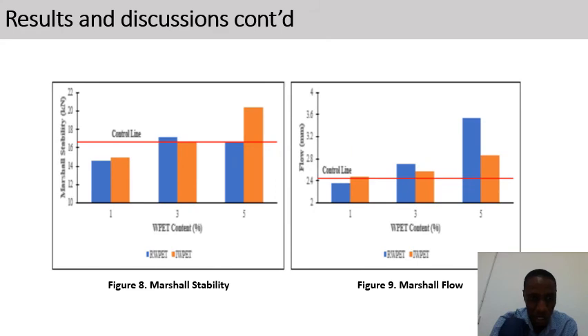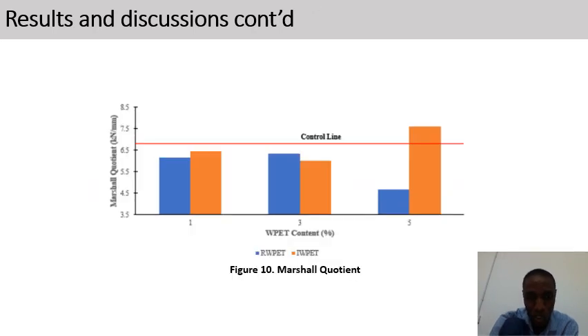As you can see, the stability increases with the PET content for both mixtures, but the irradiated PET has higher Marshall stability compared to the non-irradiated PET mixtures. This is as a result of the gamma irradiation effect, which makes the PET constantly increase, and then it covers the void between aggregate and makes the mixture stiffer. Then the flow increases with increase in the PET content, but the flow values are within the code specification of the JKR specification. The next figure is showing the Marshall quotient.